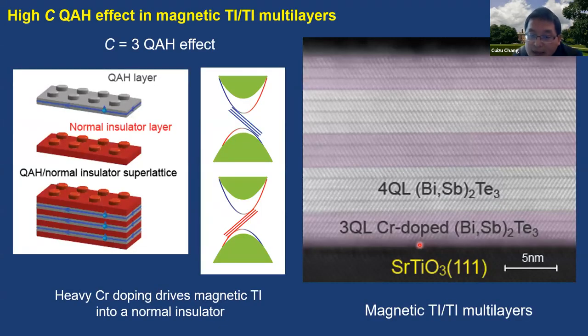And in our experiment, we realized this kind of high Chern number quantum anomalous Hall insulator by stacking C equals one quantum anomalous Hall layers. As I just introduced, this is chromium doped bismuth antimony telluride. And here is the normal insulator layers. But as an MBE grower, it's very difficult to find a normal insulator to connect the C equals one quantum anomalous Hall layers. We know that this normal insulator should share the same lattice structure as the topological insulator.